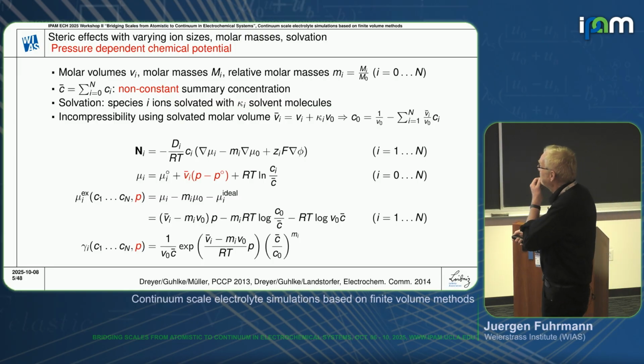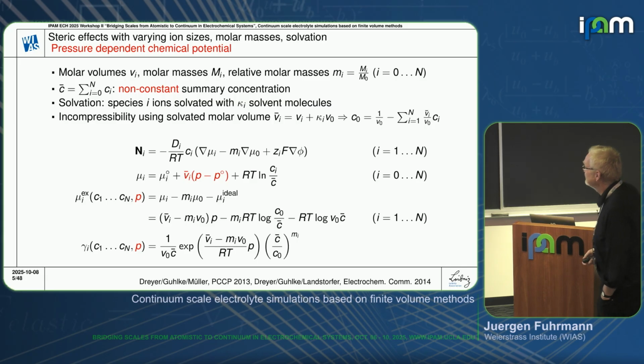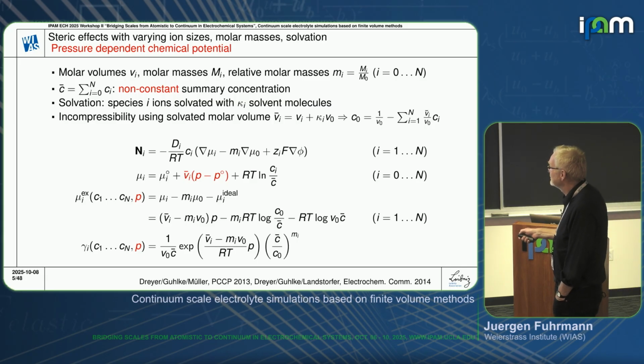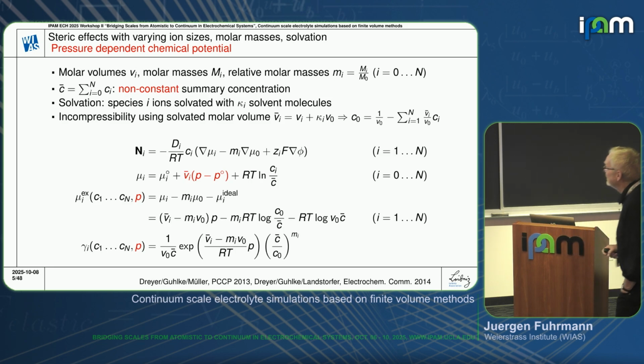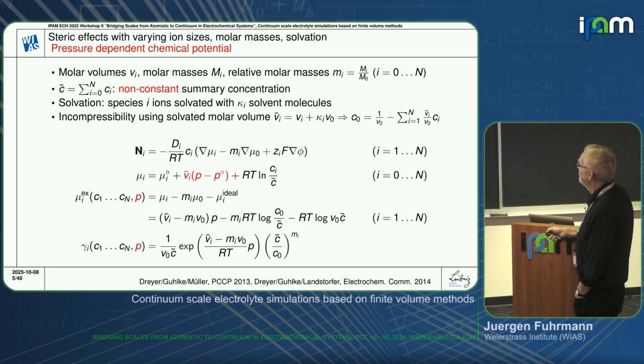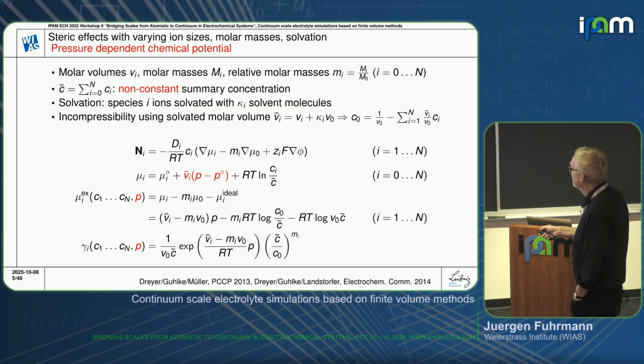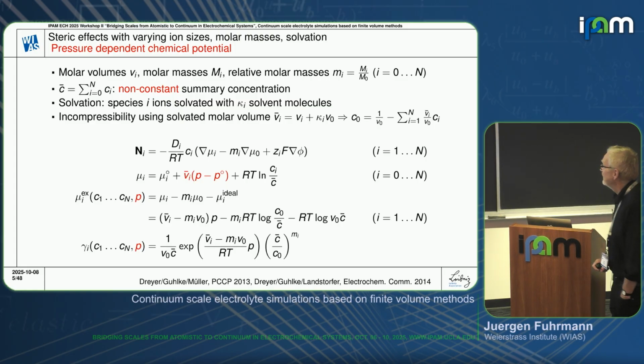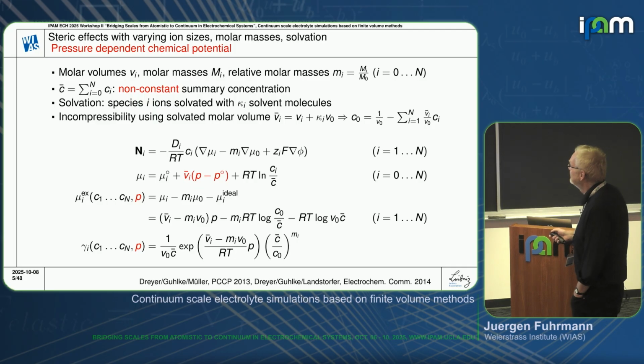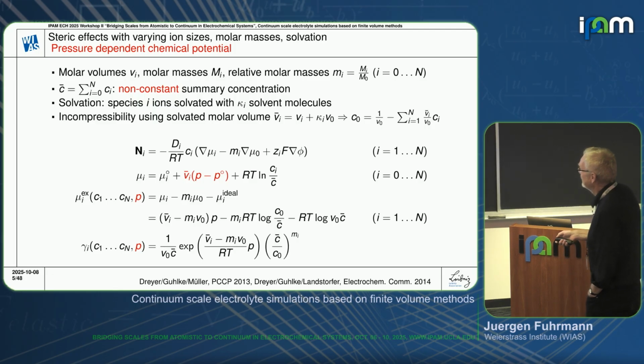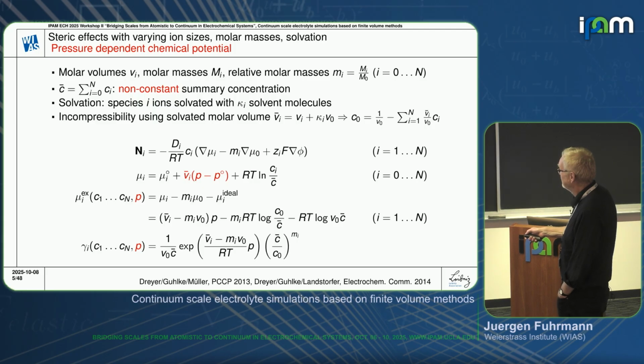We basically can assume that the ions are solvated. That means the volume which goes into our model basically is the solvated molar volume. And this goes also in the incompressibility condition here. And this then means that we also have a non-constant summary concentration anymore.